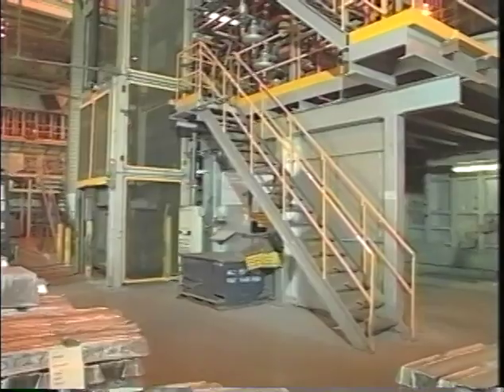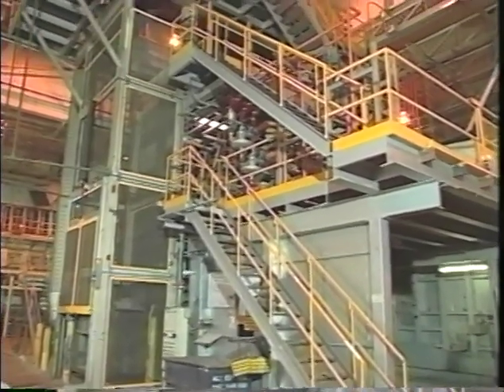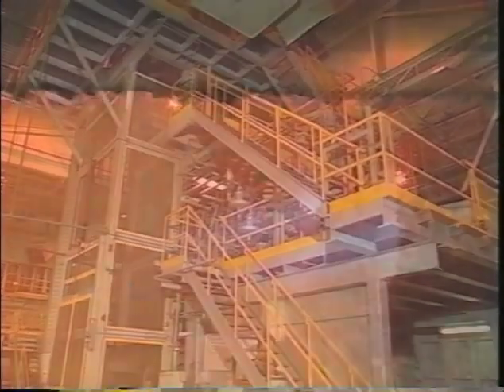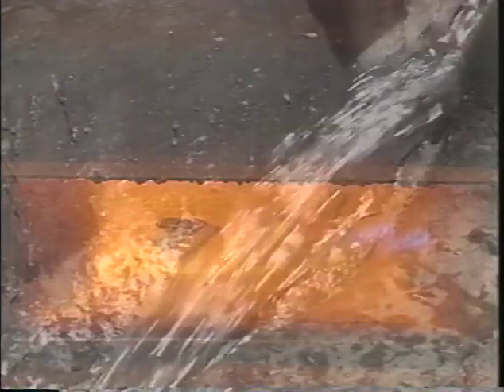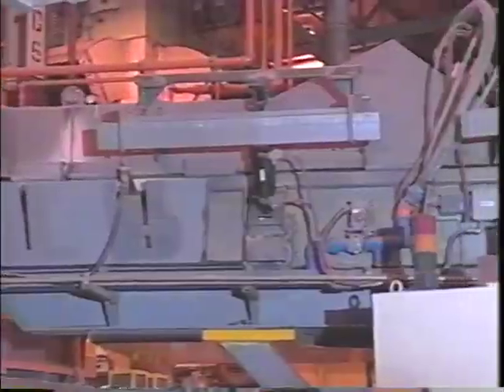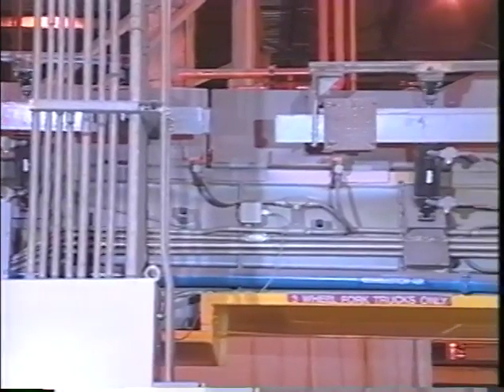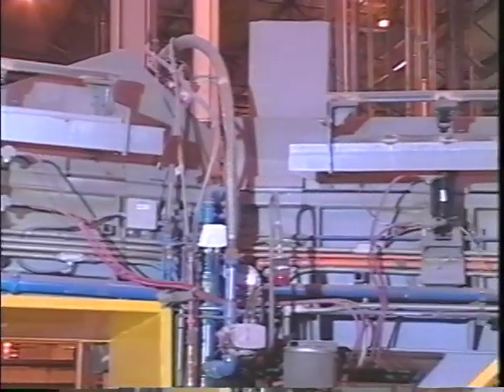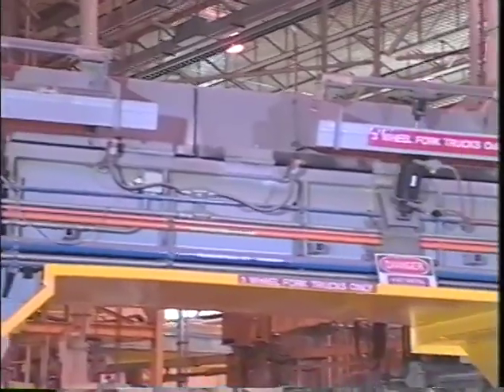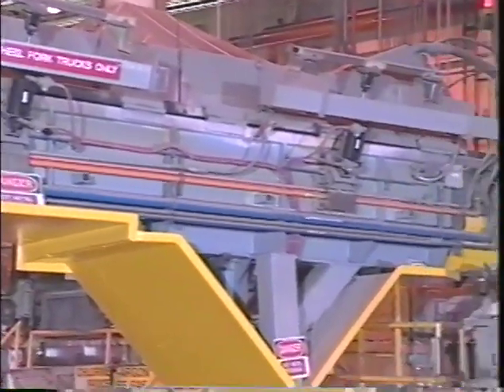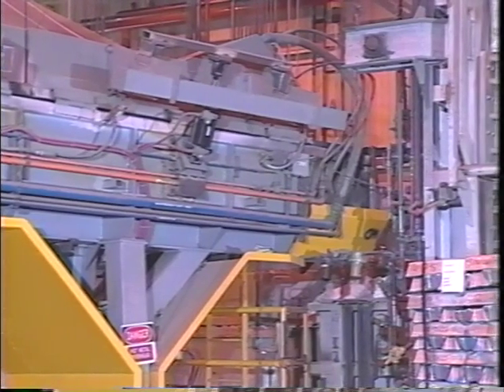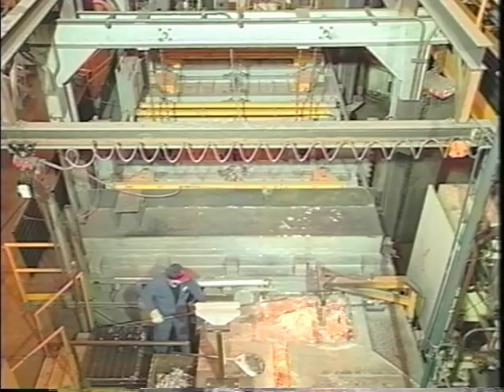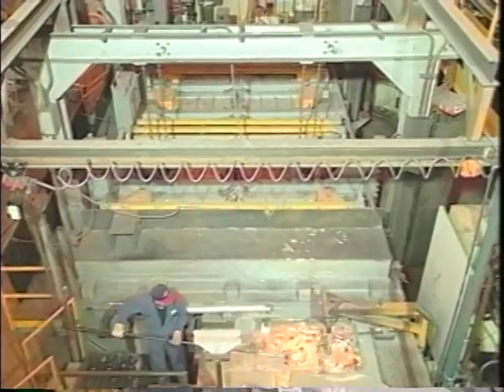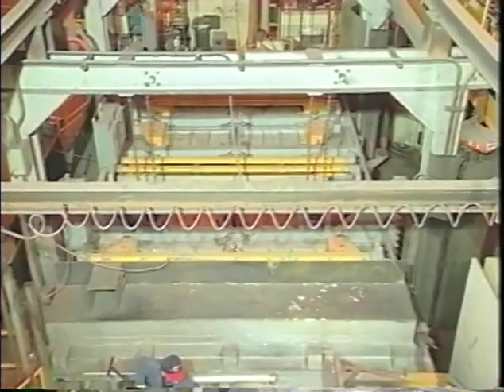Aluminum ingots are melted in the two main gas-fired furnaces, each of which holds 41,000 kilos of molten metal. If molten aluminum is exposed to air, it causes porosity and hard spots in the casting. To avoid this, the molten aluminum is contained and poured in a closed system. Instead of being transported by fork trucks in open ladles, the molten metal flows through sealed conduits called launders into the pouring furnace. This process not only improves the quality of the castings, it significantly improves the safety of the working environment. The pouring furnace holds 32,000 kilos of molten aluminum. Here, the aluminum is maintained at the pouring temperature throughout the delivery system.